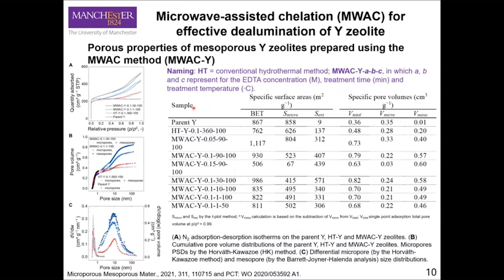So as you can see, here we show a table about the development of the materials. In the naming of the materials, HT means the conventional hydrothermal method, which takes 6 hours at 100 degrees Celsius, and we use the microwave method to do it. The ABC represent the concentration of the chelating agent we use, the treatment time, and the temperature. We found the method is very, very effective. At 100 degrees Celsius, we kept reducing the treatment time to 1 minute, and it's still very effective to produce the hierarchical zeolite with significant mesoporous features, like mesopore volume and external surface area. And if we reduce the temperature to 50 degrees Celsius, it's still very effective.